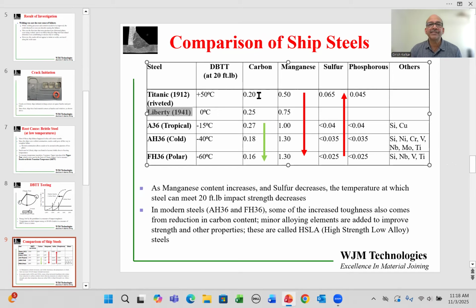And here is the chemical analysis: carbon, manganese, sulfur and phosphorus. The main two elements to keep track of are manganese and sulfur. So back in the day, manganese was only 0.5% and sulfur was 0.065. By the time of the Liberty ships, the manganese had already been increased to 0.75. I could not find data for the sulfur, but the ductile to brittle transition temperature has been reported to be close to 0 degrees centigrade, close to freezing.